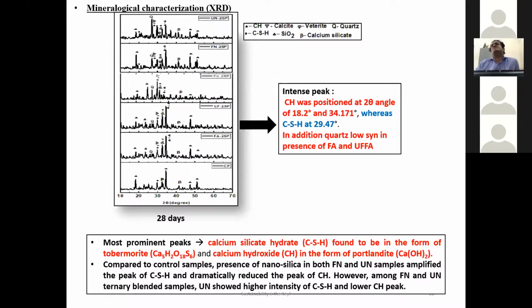Same thing for the mineralogical composition, I will not take much time, just another 5-10 minutes. When I'm going with the XRD, the X-ray diffraction, I am getting more prominent peaks for calcium silicate hydrate when I'm going with the nanoparticle admixed concrete or nanoparticle admixed cementitious composite. You can see here the peaks are too much as compared to the control mix, where the peaks are very much less. So the intensity of peaks is going to define how much your material has reacted and formed the calcium silicate hydrates or the hydration products.